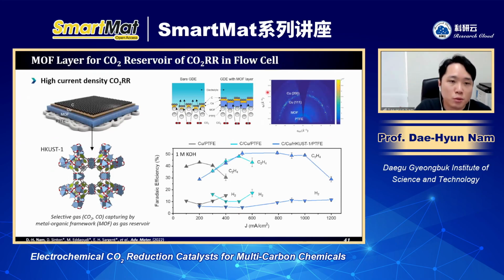And the third one would be how we can increase current density by controlling the microenvironment of the gas diffusion electrode. As I previously showed, these MOFs are very effective for capturing CO2 when they are applied to the GDE. So compared to bare copper, MOF-incorporated GDEs are very effective in increasing the partial current density of ethylene.